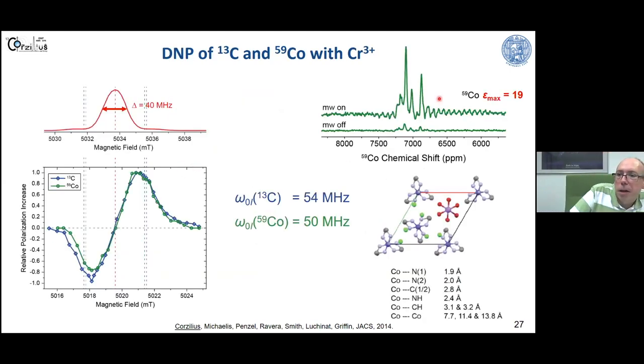Using this, you can not only hyperpolarize carbons in the organic ligands, but you can also directly hyperpolarize the cobalt-59, which is situated on the neighboring complexes the chromium has been doped into. This is quite interesting because they are at least about 8 angstrom away. So this is pretty direct proof that we can transfer polarization at least over a distance of 8 angstroms, if not even larger.